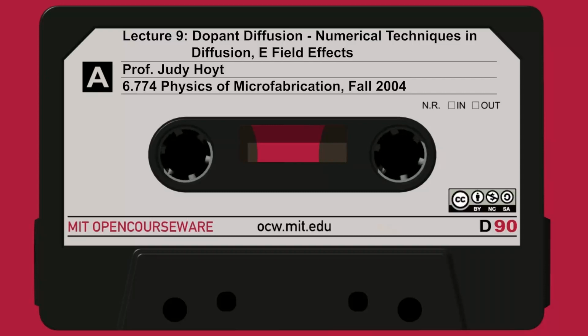So H is not going to be any larger than 2, and that means that the electric field enhancement term can enhance the diffusivity of the dopant that causes the field by as much as, or a maximum of, a factor of 2. And this happens when the dopant concentration term, C, is much, much greater than Ni. And you can see that by substituting in and calculating out what H is in certain conditions. In the special case where C is much less than Ni, then H goes back to being equal to 1.